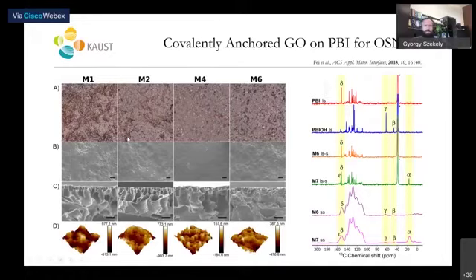It is notoriously difficult to follow the GO distribution in a polymer matrix. So we came up with a simple solution that you can see here in the first row. We used optical microscopy. And as you can see, the GO flakes are actually shiny. And this is where you can see how well your GO is distributed. Otherwise, you can see the surface of the membrane, which is quite smooth, and you can see the cross-section, which is a typical ISA or asymmetric membrane structure. We looked at the carbon solid-state NMR to verify the presence of the cross-linking and also the presence of the GO.